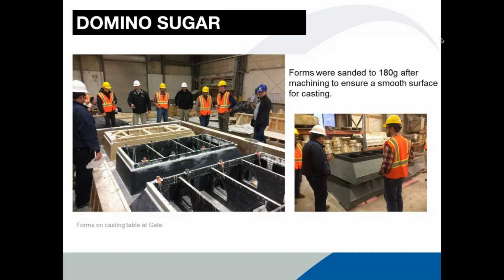On the right-hand side, you can also see in the smaller picture that after they had been machined, they were sanded with about 180 grit. They might have sanded them a little further than that, but the plastic is easy to cut and easy to sand if you really want to. At AES, we've even buffed some molds up. A lot of molds don't need that high of a surface finish, but it's able to get that high. For this project, I think we were somewhere between 180 grit and 220 grit for a form surface.